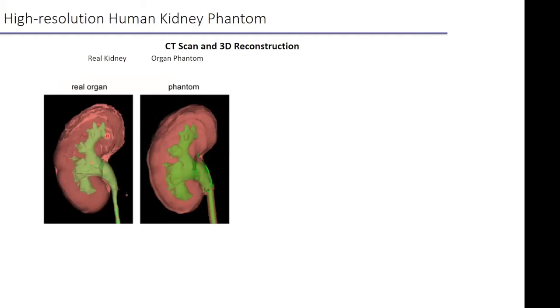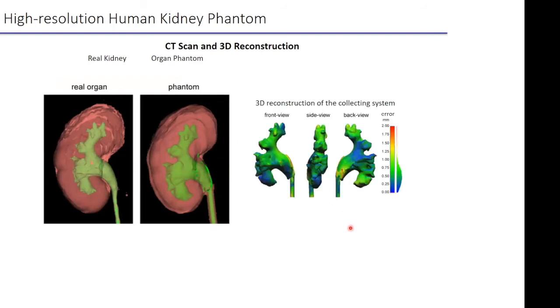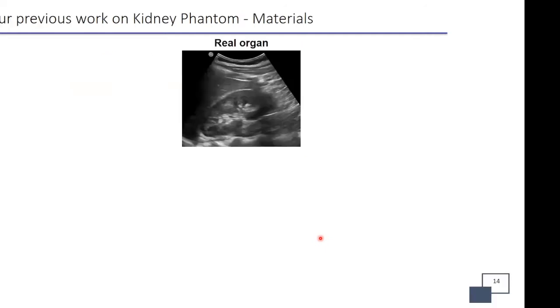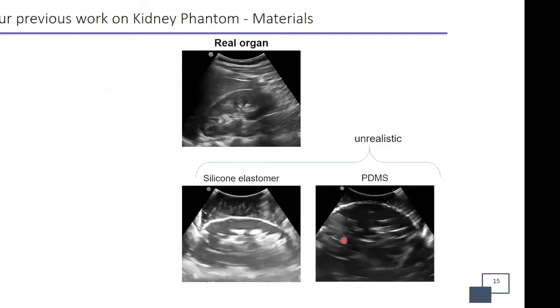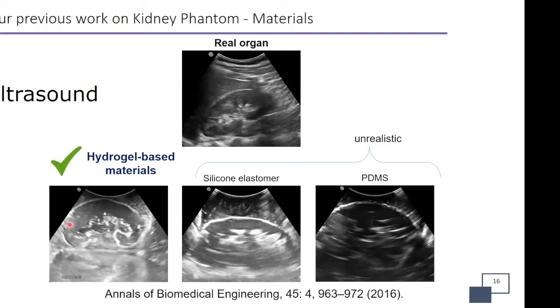So there are CT scans of the real organ and the phantom after we made it. And the error is below a millimeter. So we're talking of 500 micron errors, and we can get a lot of anatomical detail that is missed, as far as we know, pretty much in every model you can buy. And furthermore, because we can choose materials for the fabrication, we can get the right imaging contrast. So if you choose materials like PDMS or silicone elastomer, you can see that the ultrasound image is completely useless. It doesn't really reflect the organ. But for instance, if we make our organs out of hydrogel materials, we get very nice looking images that are, to a surgeon, as good as the real organ.